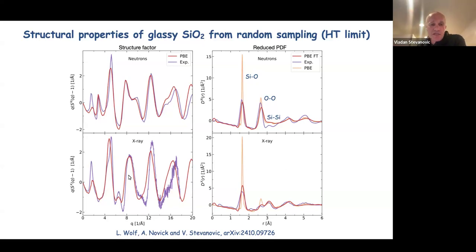What I'm plotting on the left is the structure factor, as measured by neutron diffraction or X-ray diffraction experiments. It's not exactly the structure factor, it's actually Q(S(Q) minus 1), the quantity that, when you Fourier transform it, you get what is called the reduced PDF. So the right panel shows the quantity called the reduced pair distribution function. That is the direct sine Fourier transform of this quantity. In orange, you find the one directly calculated from our real space structures. And then in red, what you find is doing the Fourier transform on the left curve as experiments would do, and how well these things agree with experimental results.